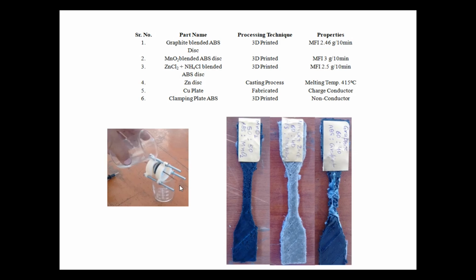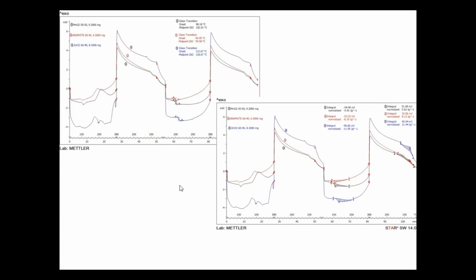Then suddenly we decided to charge this battery. How to charge this? I have an ABS in which MnO2, then ammonium chloride and zinc chloride powder, then graphite powder were reinforced and printed in the form of different discs. But ABS is basically an insulator, so it is not allowing the charge to flow for the chemical reaction. So what we did is put some drops of acetone into it, so that the interface between the different discs is removed, right? Once we put just a few drops of acetone, we were able to get an immediate 1.5 volt. We were so fascinated to see the output, and there were a few good observations for this.